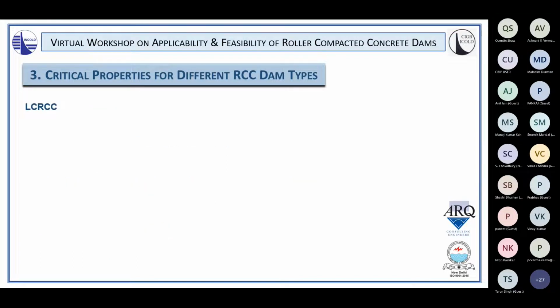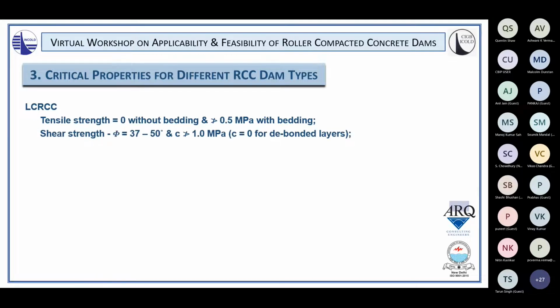So with lower cementitious RCC, we have a situation with tensile strengths typically assumed as 0 where no bedding is used, and maybe as much as 0.5 MPa at the top end when bedding might be used. Shear strengths will typically be friction angles of between 37 and 50 degrees, and cohesions between layers would not realistically be more than 1 MPa, and that number could be as low as 0 when debonding between layers is observed. This will give you a permeable RCC matrix unless bedding is included between the placement layers, in which case impermeability can be created.